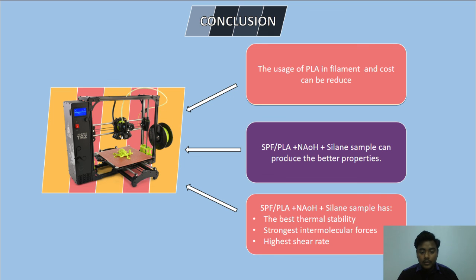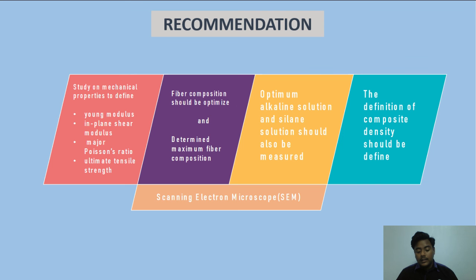the sample that goes through both treatments, which is NaOH plus silane treatment, has better properties than pure PLA or the other samples. This sample has the best thermal stability, from the data gathered from the DSC and TGA analysis, and it has the strongest intermolecular forces because it has gone through two treatments. And the last one, it has the highest shear rate, which has been proved from the rheological data.